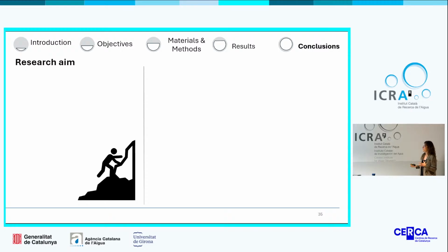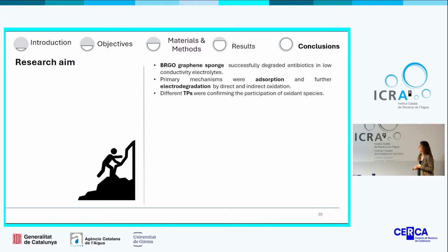Taking back the research aim of the project, which was the synthesis of different 3D graphene-sponge electrodes doped with boron, nitrogen, and sulfur to get a successful inactivation of antibiotics and bacteria, we could affirm that BRGO graphene-sponge successfully degrades the antibiotics in low conductivity electrolytes. The primary mechanisms were the adsorption and further electrodegradation of the contaminants through direct or indirect oxidation, and different transformation products confirmed the participation of some oxidant species.